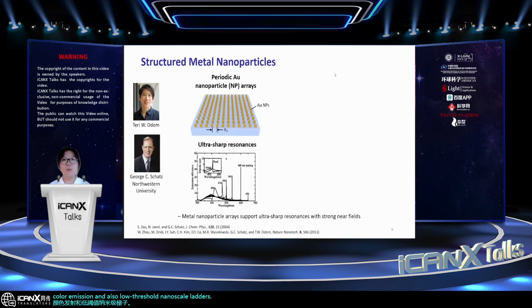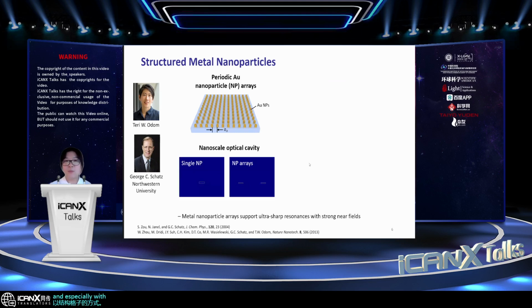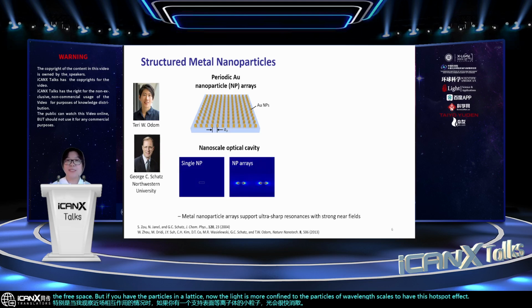The system we utilize is based on such unique particles in an array. This dates back two decades ago to Schatz's group at Northwestern, where they observed really ultra sharp resonance when you have the particles in a structured lattice fashion. Especially when you look at what is happening in terms of near-field interactions: if you have a small particle that supports local surface plasmons, the light will dissipate pretty quickly to the free space. But if you have the particles in a lattice, now the light is more confined to the particle subwavelength scales to have these hotspot regions. And what you see here is a characteristic standing wave pattern from such an array structure.